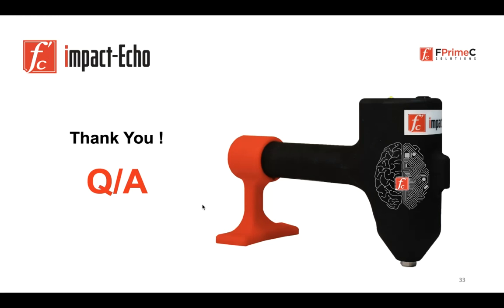Yeah, and I think this would be our final question for now. Can you estimate the concrete strength and other parameters using impact echo? For the concrete strength, there is a European code. And based on that European code, yes, you can use your P wave velocity plus the Schmidt-Hammer results. And based on the model, which is proposed by the European codes, you can estimate the compressive strength of concrete. So impact echo needs to get complemented with the Schmidt-Hammer. You need both results. And then go with that mathematical model.